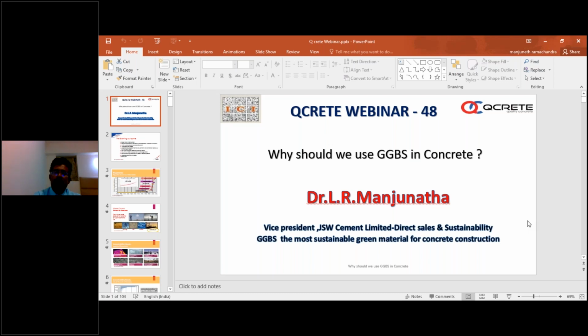The next question is, while using GGBS in concrete, if stripping of vertical elements is delayed by 24 hours, is there any impact on the concrete? No, generally you are designing the grade of concrete for stripping purposes. Like now, people are making U-troughs for Bangalore Metro using GGBS. It's not GGBS alone that will affect your stripping time. It depends on how you are designing the concrete mixes and how you want to attain the strength. Somebody says I want 18 MPa strength in 12 hours' time. People are designing that, and they use 30% GGBS. So the stripping time and strength requirement all depend on the grade of concrete and how you are designing the mixes.